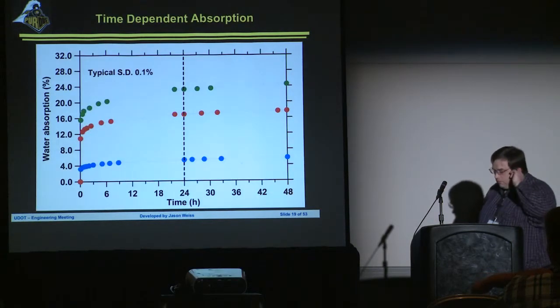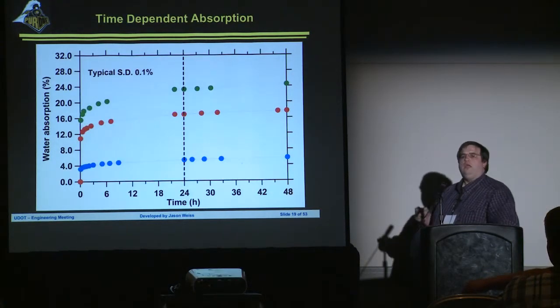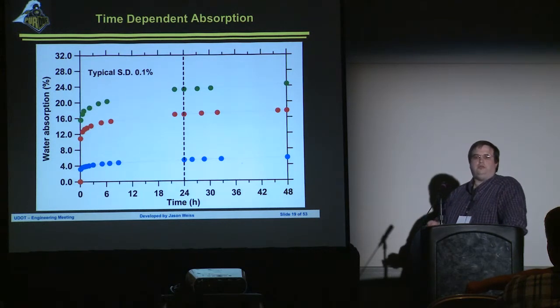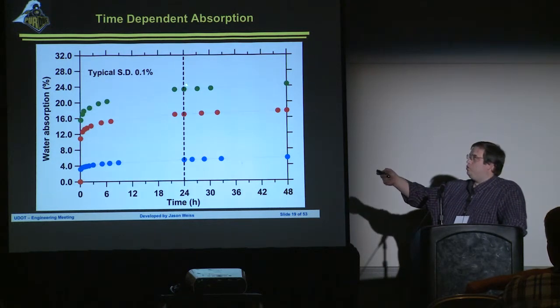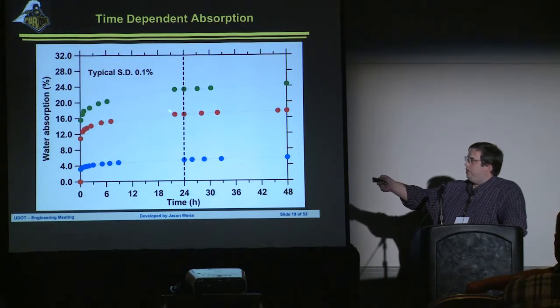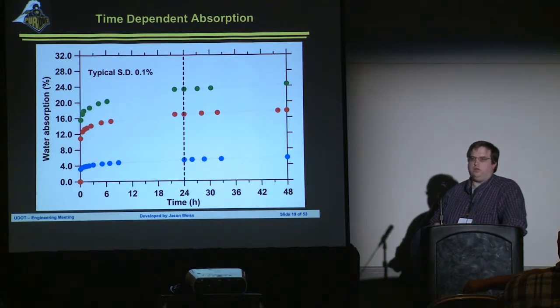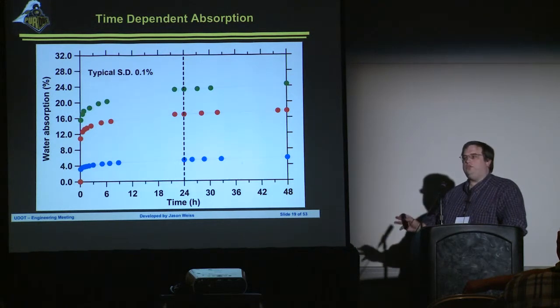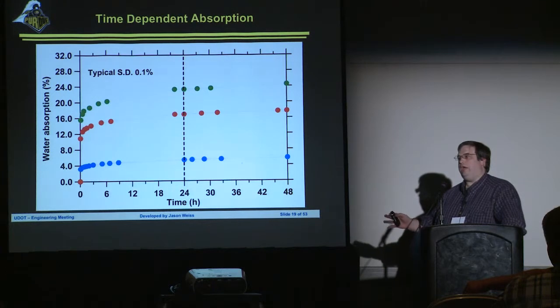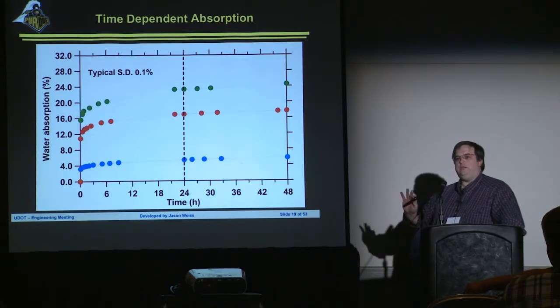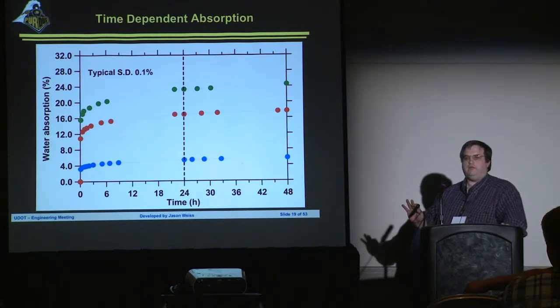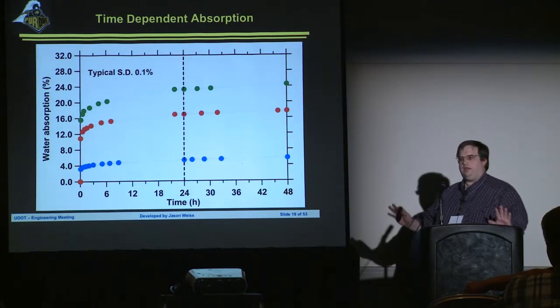Now, as I mentioned before, there are about 18 different sources of aggregate to be used. They have very different absorptions. One that's probably typical to Utah is right around in here, where you've got about 17 or 18% absorption at 24 hours. They can all be used to internally cure your concrete. The only difference is how much lightweight aggregate you're going to use. And in general, there's an equation, and if anybody wants to see the derivation of the equation afterwards, I'll be happy to discuss it at great length with you.